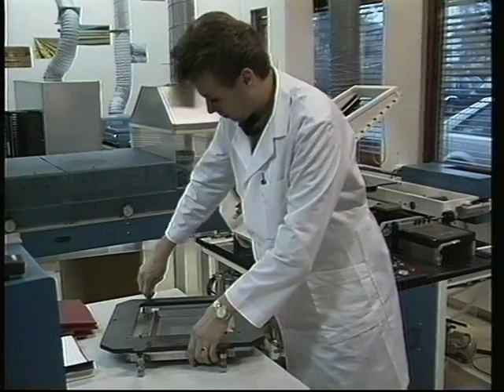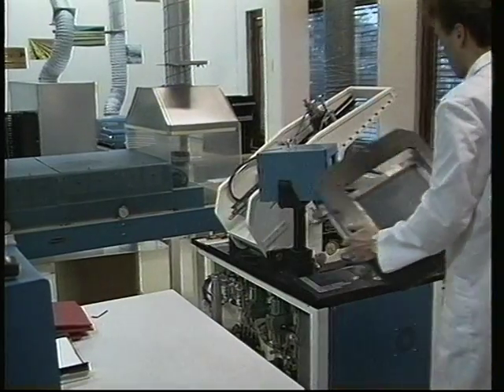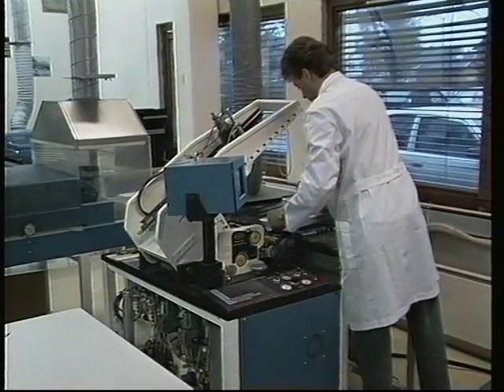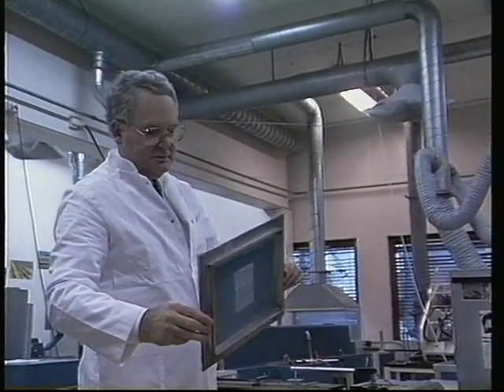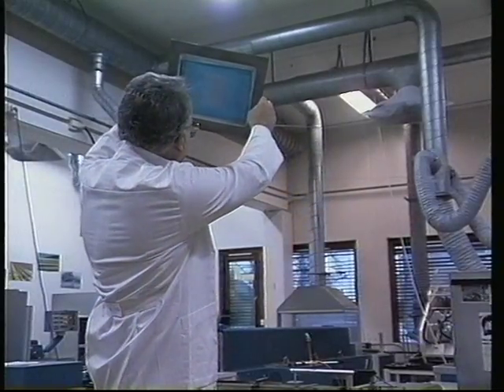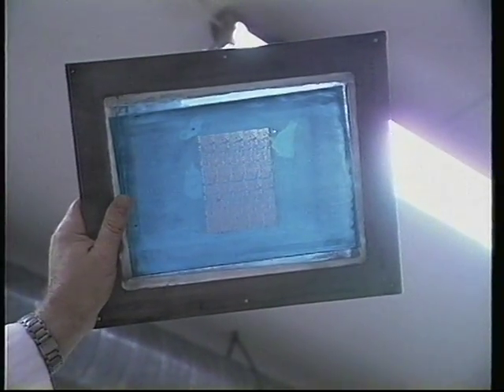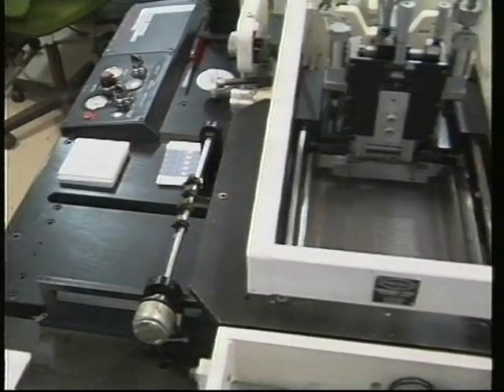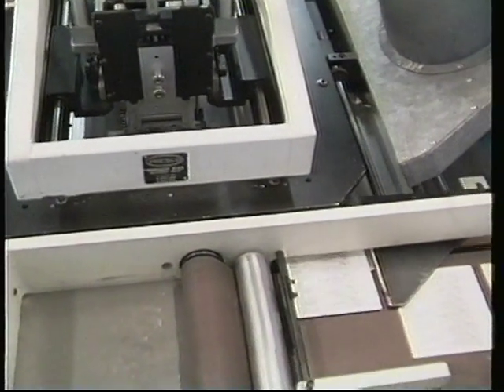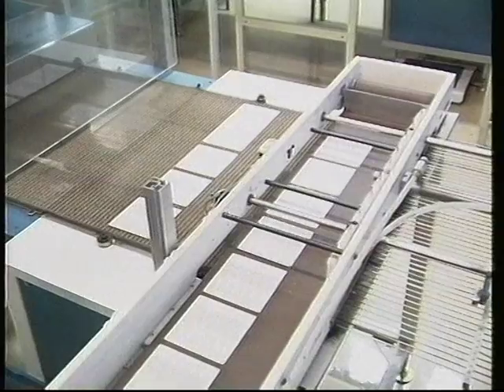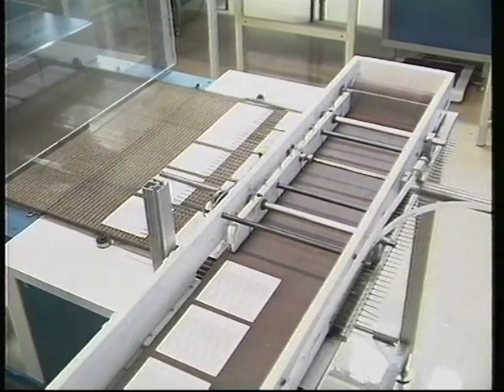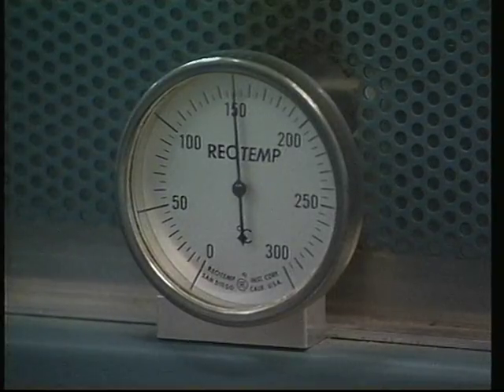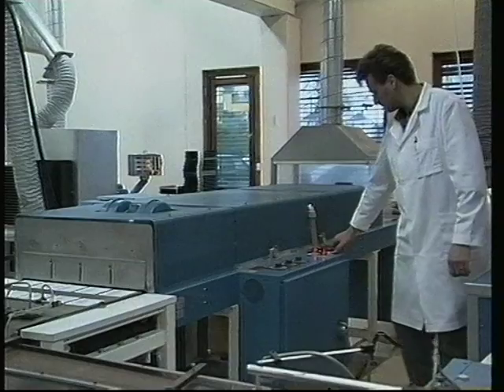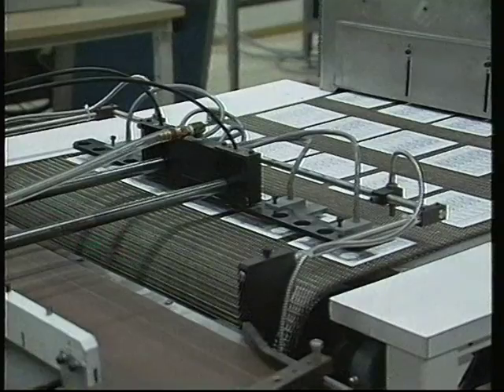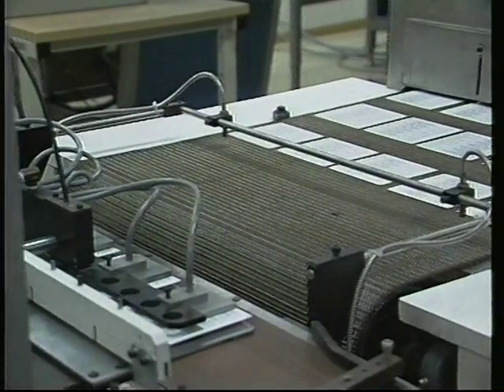The various circuit materials are deposited on the ceramic substrate by screen printing. The screen itself is made of thin, woven stainless steel wires and is masked by a photosensitive organic film. The first step is printing of conductor layer number 1. After printing, the drying process takes place. The furnace heats the circuits to 150 degrees centigrade for 10 minutes. The volatile components of the printing paste evaporate.